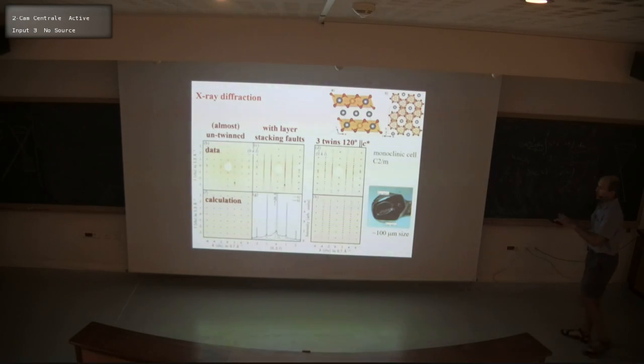So it was only through very careful selection of crystals that we were able to tell that the crystal structure is not actually threefold symmetric with a trigonal space group, but is monoclinic. And in the end, the crystals that come out are still quite small, about 100 microns, or still sometimes a bit bigger. But really, they're not suitable for neutron diffraction. So what I'm going to show next is how we use X-rays, in particular resonant X-rays, to probe magnetic ordering.